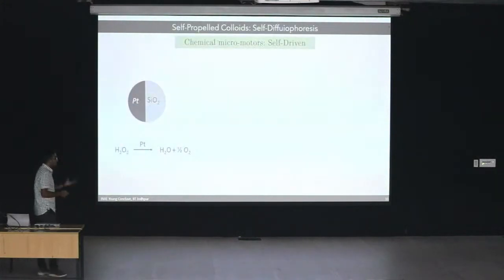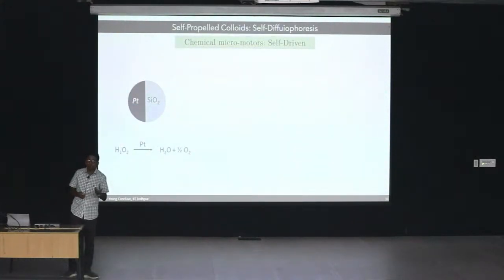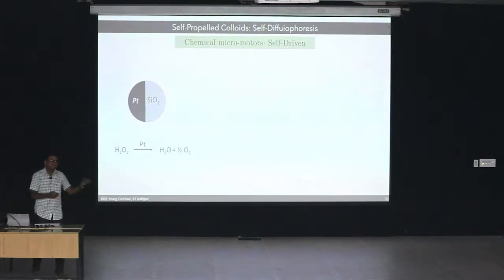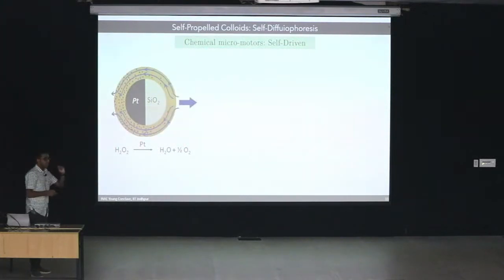But how do we create motion in these self-propelled Janus particles? Right? We have Janus particles, how do they self-propel? So the idea is that, let's say we start with a platinum silica Janus particle, a simple spherical Janus particle. If you put this particle in any medium and add hydrogen peroxide to it, hydrogen peroxide reacts on this platinum surface and undergoes this reaction. So silica is not undergoing that reaction, but platinum is. So the reaction is asymmetric. Hence, the reaction product's distribution is also asymmetric.